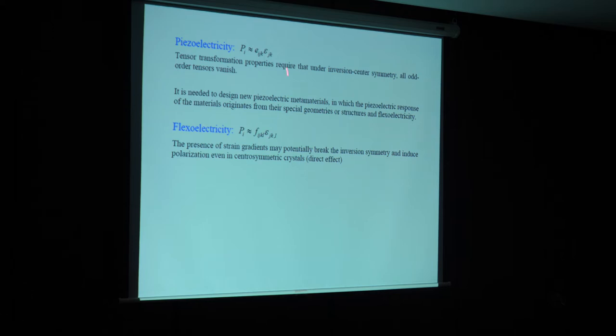Flexoelectricity is phenomenologically similar to piezoelectricity, where a polarization vector is proportional to the strain gradients. And you can see that this flexoelectricity coefficient is tensor of the fourth order. And this non-symmetric value is observed also in the material where it is symmetric arrangement of atoms.